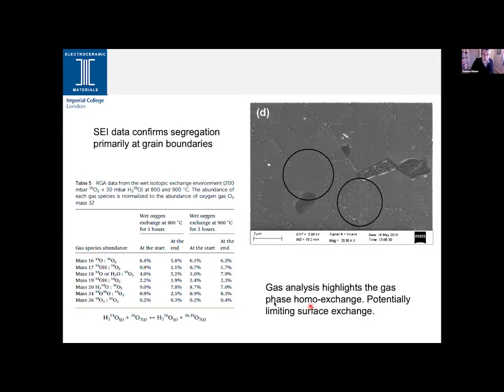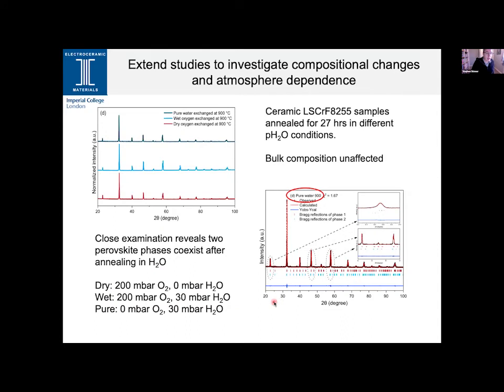moves along, and my computer, I'm afraid, is running remarkably slowly. There we go. So now we have some diffraction data of the three samples. Three samples, one of which is dry oxygen exchanged, one of which is wet, and one of which is under the pure water, so essentially a reducing condition.